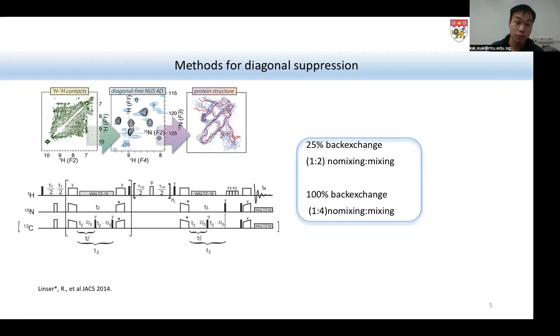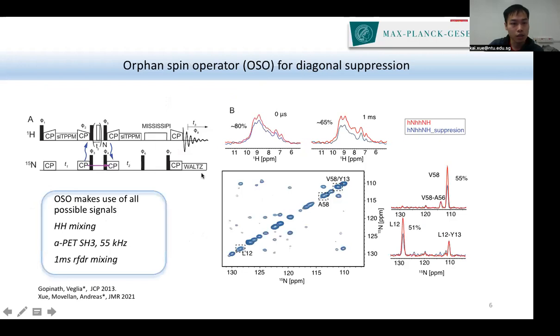So this scan doesn't contribute to the final sensitivity of detection. So what we proposed here is a small modification on the CHHC or NHHN scheme. On the left side here is the pulse sequence. We have a single transfer CP from H to N, N to H, and mixing H to N again, and N to H, and then backward detection. In your original pulse sequence, we do not have these two pi pulses.